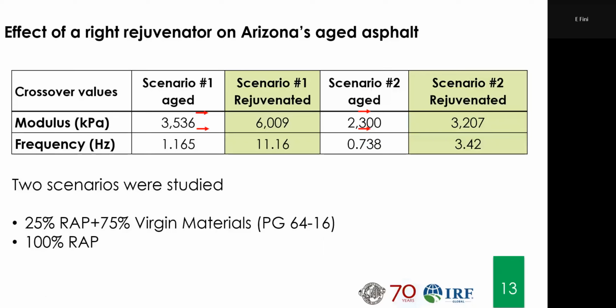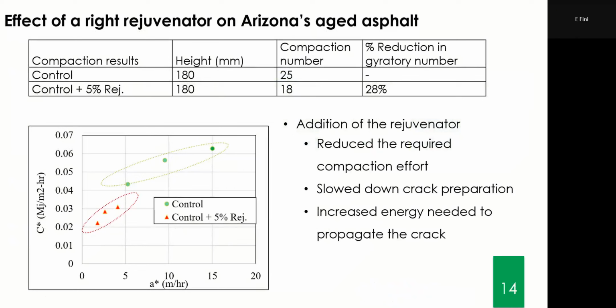Then one other thing is when you look at the different scenario here for aged rejuvenated asphalt, the modulus and frequency, we studied them with the actual RAP. So we had 25% RAP and 75% virgin material, and in one scenario, we had 100% RAP. In all of those scenarios, you can see the change as the rejuvenation was taking place. This is actual RAP from the road. So the effect of rejuvenator in Arizona aged asphalt was very noticeable. Arizona's asphalt is highly aged because we have many days of sun and high temperatures above 100 Fahrenheit. So in this case, we actually get very aged asphalt.